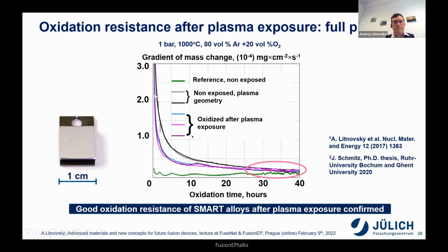And here, in this graph, which shows the gradient of change of the mass during the oxidation, we were first alarmed because the initial ideal samples, which I showed, these cubic bricks, have a very tiny change of mass because of oxidation, whereas the plasma samples show quite a large one. And we started to investigate why this is so. It appeared the matter is not the material itself, but its shape.